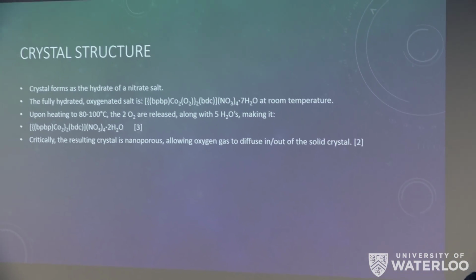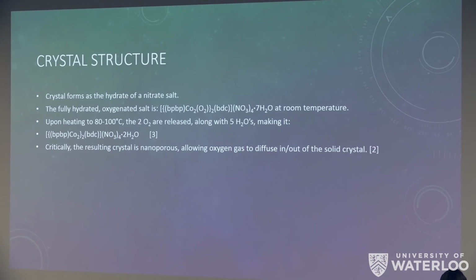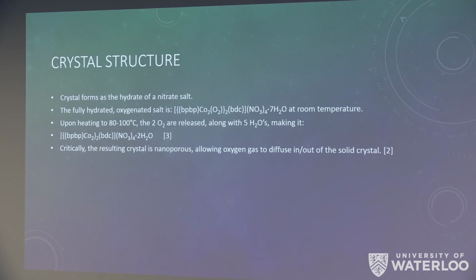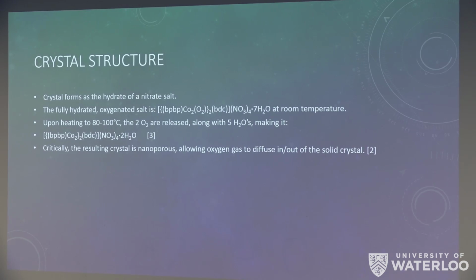At room temperature, as mentioned before, this crystal is a hydrate. It's a heptahydrate of the nitrate salt, meaning that it's coordinated with 7 water molecules in the natural crystal state. At this temperature, it will also aggressively absorb 2 diatomic oxygen gas molecules by forming bonds with the cobalt, which is at this point believed to be in the 3rd oxidation state. Upon heating to 80 to 100 degrees, it will lose these oxygens and 5 of the 7 water molecules, becoming a dihydrate. Its crystal structure stays mostly the same, although the cell diameters change.